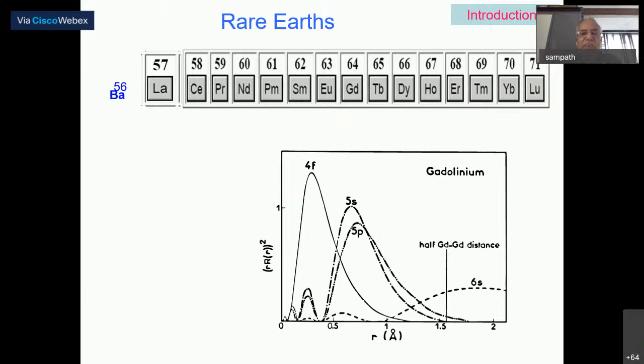Okay, for the benefit of some students who are at the beginning of their career, just 5-6 concepts will be very, very elementary. Please pardon, experts should pardon me. As we go from lanthanum to lutetium, what is really varying is essentially the 4f electron count. It was believed for a very long time that the 4f orbitals are strictly localized, as seen in the radial distribution function as a function of the distance from the nucleus. You could see the 4f orbital is very much deeply localized compared to 5s and 5p, which are essentially the outermost orbitals in a rare earth ion.